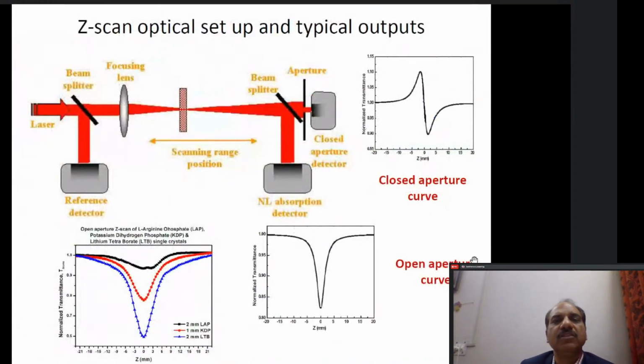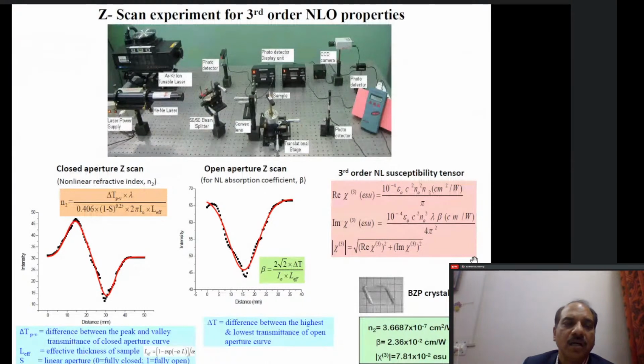Z-scan is another technique which we use for finding out the nonlinear refractive index and nonlinear absorption of NLO materials, and this is the setup which we have used. We use it for closed aperture Z-scan and open aperture Z-scan. Closed aperture Z-scan gives us the n2 value, which is the nonlinear refractive index, and open aperture Z-scan gives us the beta value, which is the nonlinear absorption coefficient. By finding out these nonlinear refractive index and nonlinear absorption values, we can find out the third order nonlinear susceptibility through this formula, in which the only experimental values are n2 and beta; all other values are constants.